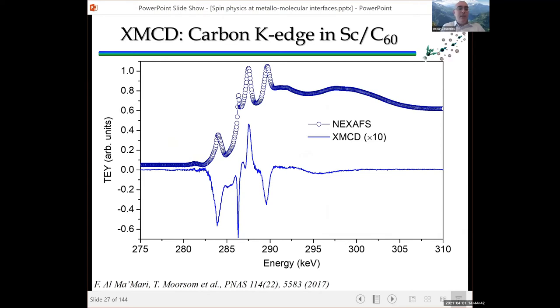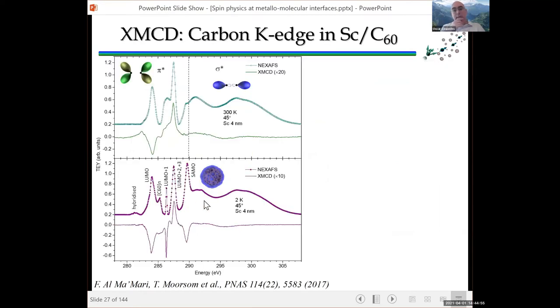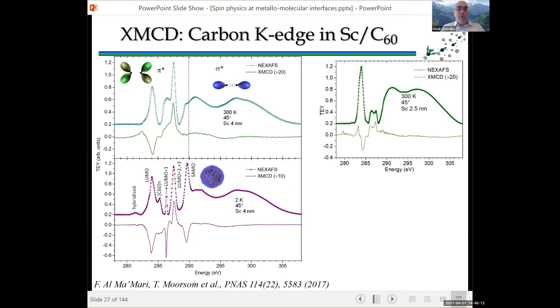In this case, we did measurements of scandium with C60. And as you can see in the carbon edge of C60, you can clearly see dichroism indicating that the carbon is indeed becoming magnetized, mostly we think an orbital moment rather than a spin moment, and localized to the pi star antibonding orbitals of the molecule rather than the sigma star orbitals of the molecule.